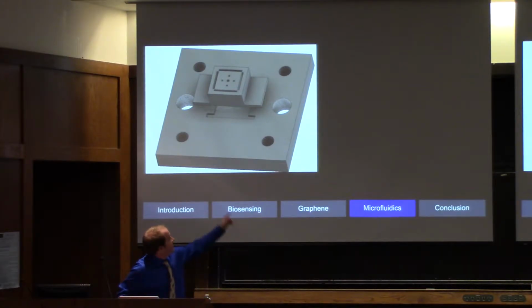And then the lid, the piece that you see on top, is for holding the PDMS with the channels. So the 4 holes that you see around the center of the lid are for the input and output holes for the fluid, and the middle hole is for the electrode, so that we can continue running the gate voltage measurements. The top piece is clamped to the bottom using nuts and bolts threaded through these holes on either side of the base. And the 4 cuts on the top are for putting our gold pins through, so we can reach the contact pads to measure the resistance.